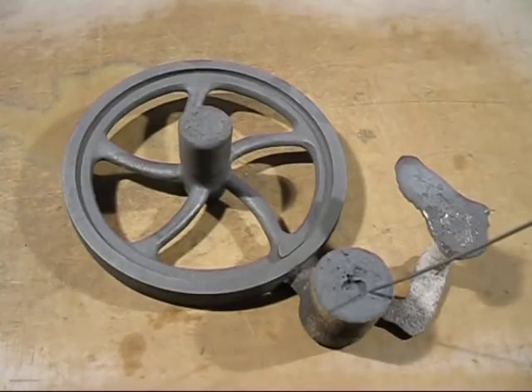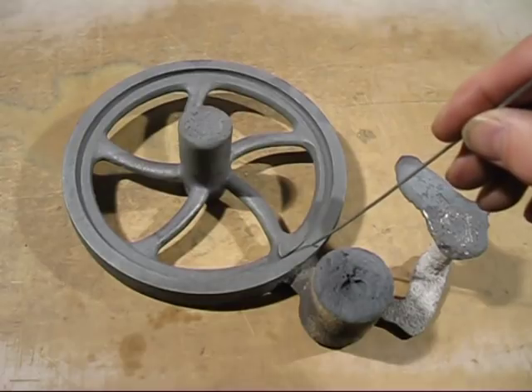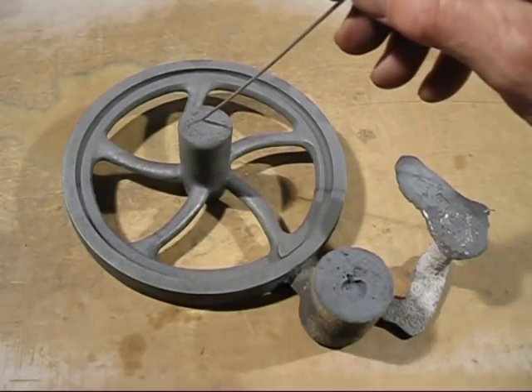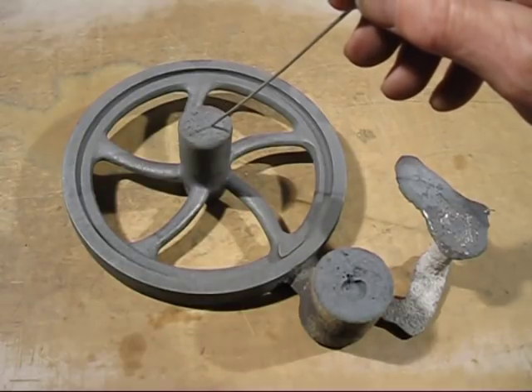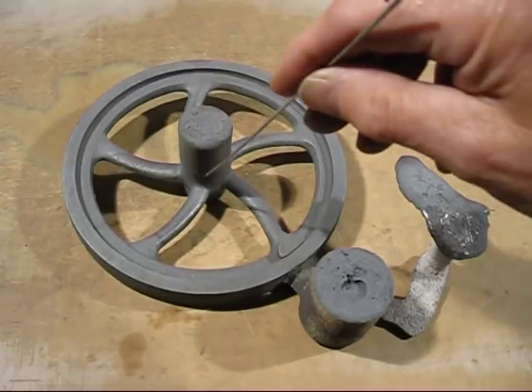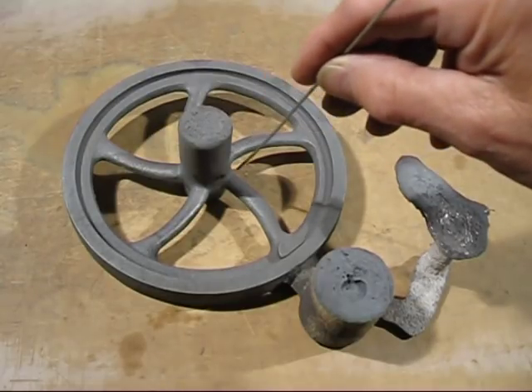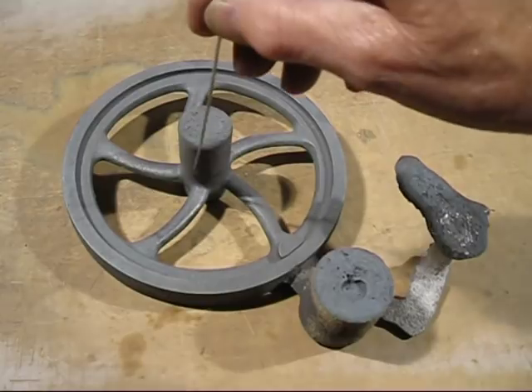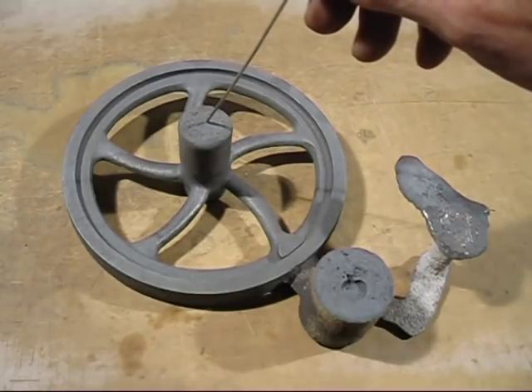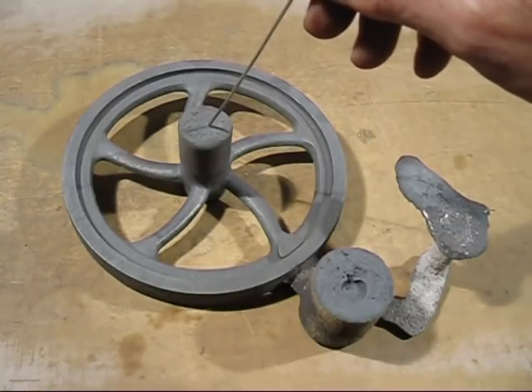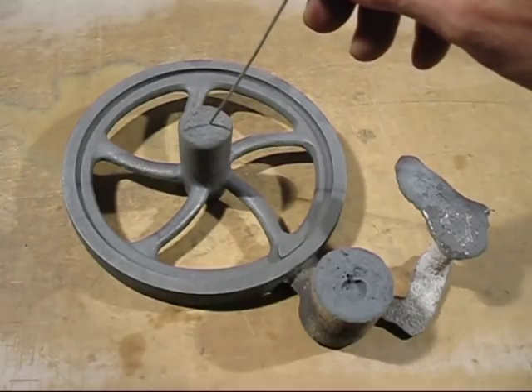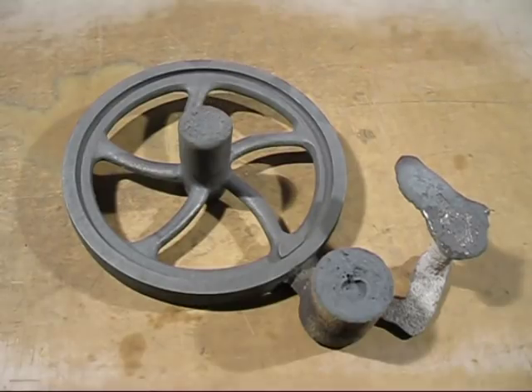This one's larger because you've got to feed the rim. But this one here, I have experimented in making them smaller, but I've always had shrinkage dimples in the edges in here and also in the top part of the boss. So I found through experience that you have to make this a little bit larger because it's a cold metal riser. This casting was the third mould, also the last mould.